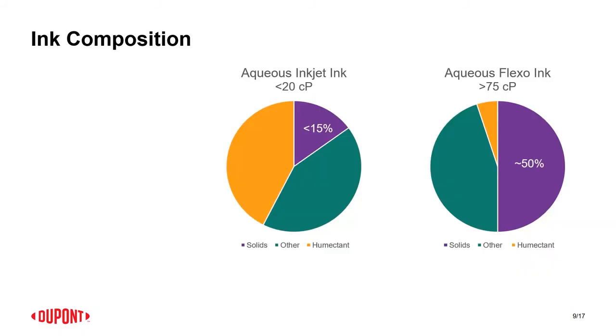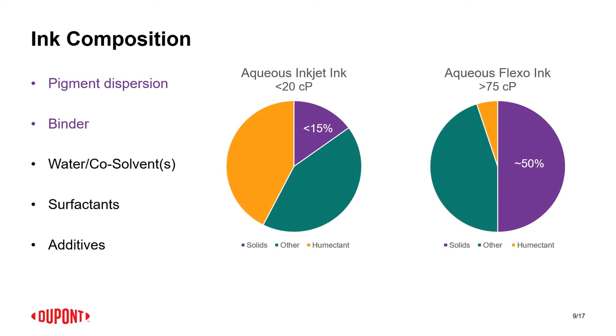Well, if we take a quick look at what's in an ink, right? And this is, for instance, right? This doesn't represent every flexo ink or every inkjet ink. It's just an example. But you can see with aqueous flexo inks that may be used today in more traditional analog processing on things like flexible film, your solids, which are typically your pigment dispersion and your binder, can make up to 50% of that particular composition with viscosities that can go into the hundreds of centipoise. For aqueous inkjet, your solids are typically no more than about 15% of your composition with a much lower centipoise, right? So then when you look at all of the other components that are in the ink, right? So your co-solvents, your water, your surfactants, and your additives.